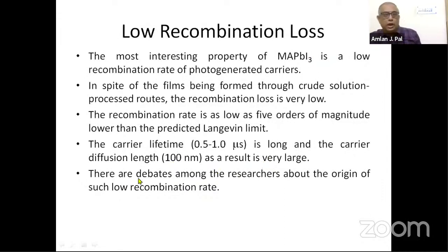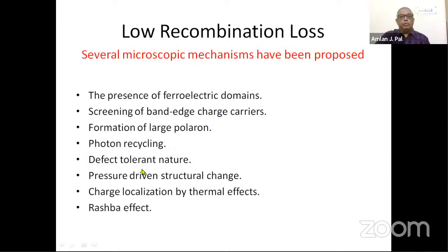So, this is the present research: there are debates among researchers about the origin of such a low recombination loss or recombination rate. There are several models going on: ferroelectric domains, screening of band edge carriers, formation of large polarons, photon recycling, defect tolerant nature, then pressure driven structural change, charge localization by thermal effect, and Rashba effect. That is Rashba band splitting. We have recently worked on Rashba band splitting, and I will explain how this Rashba band splitting can explain this low recombination loss in methylammonium lead iodide.